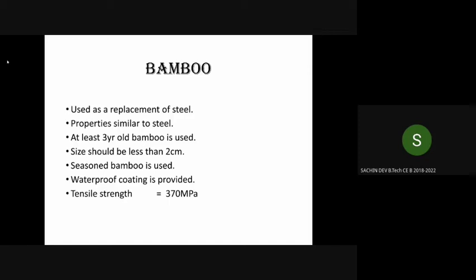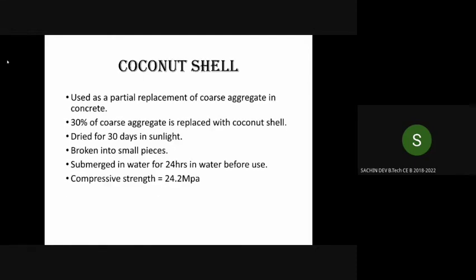The size of the bamboo should be less than 2 centimeter, and it should be seasoned bamboo. For seasoning, the bamboo is kept under the sun for about 4 weeks, and the bamboo is provided with a waterproof coating. And the bamboo provides a tensile strength of 370 MPa.